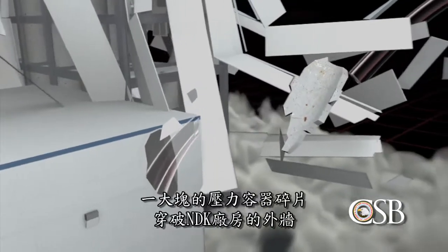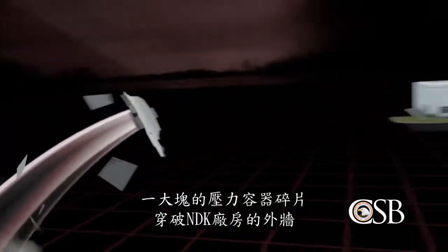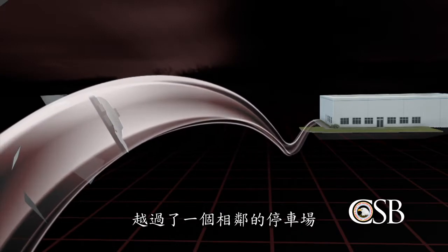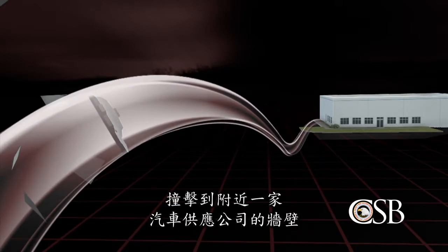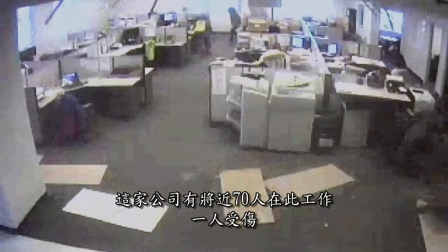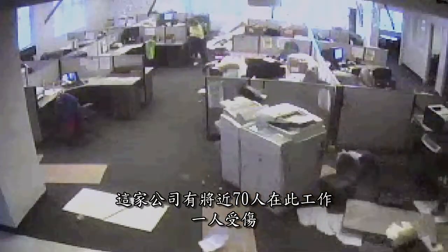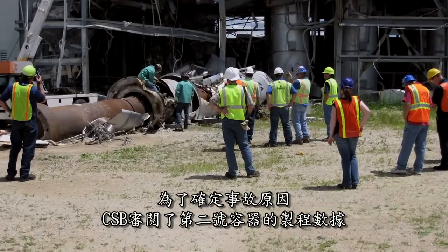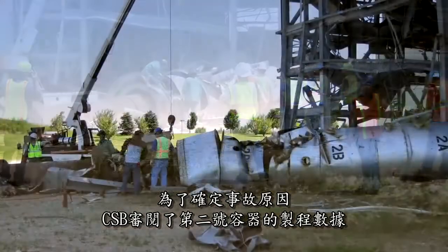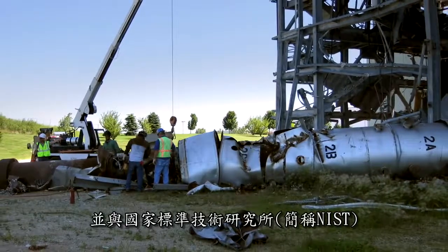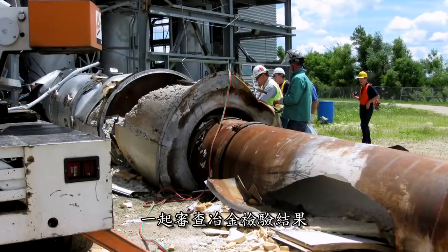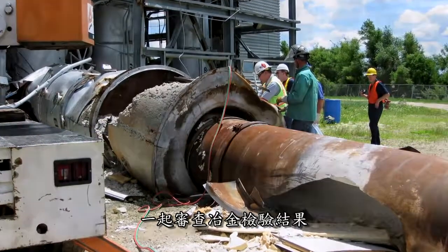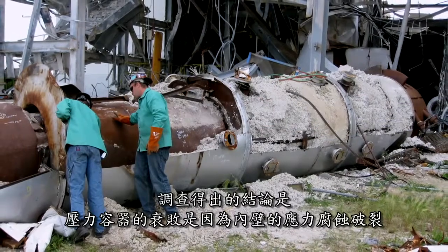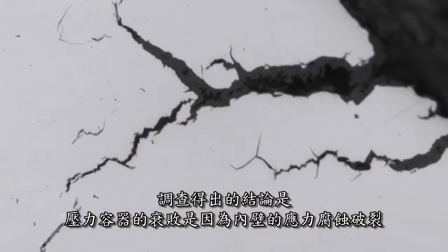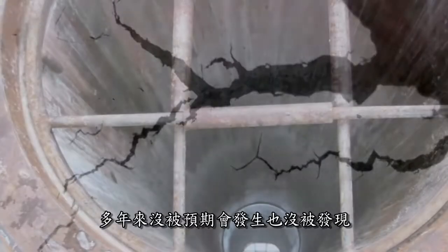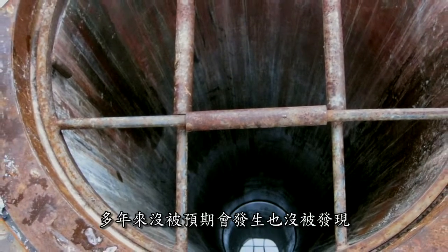A large piece of the pressure vessel tore through an exterior wall of the NDK facility, skipped across a neighboring parking lot, and struck the wall of an adjacent automotive supply company where nearly 70 people were working. One was injured. To determine the cause of the failure, the CSB reviewed process data from vessel number 2 and worked with the National Institute of Standards and Technology, or NIST, to examine results from metallurgical testing. The investigation concluded that the failure most likely resulted from stress corrosion cracking on the inside walls of the vessel, which had gone uninspected and undetected for years.